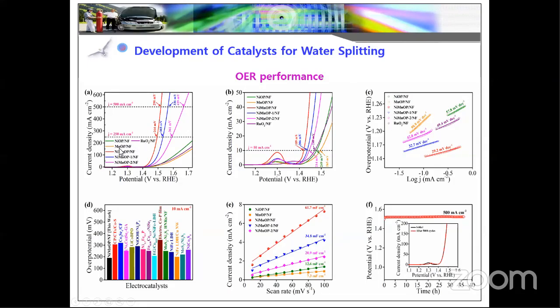From the OER performances, first we show polarization curves for different active materials. Especially, you can see ruthenium oxide is the commercially available material. We are comparing with it on the overpotential, which one is very close to 1.23 V, the overall water splitting potential. Lower overpotential means it is highly active towards the OER compared to the other counterparts, and it outperforms the commercial ruthenium oxide based materials.